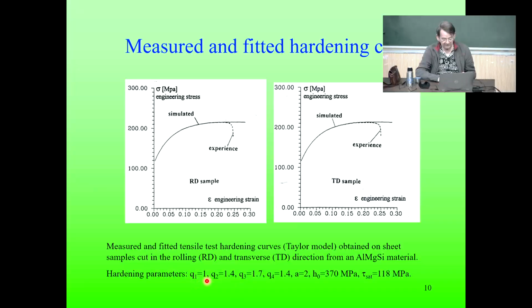We have the 4 self and latent hardening parameters. We have the initial strength of the material. Tau sat is the material tau sat, and then the rate hardening, and then the A parameter. That's it, and it is reproducing perfectly. Once these parameters are obtained, that's a separate exercise, then they are used in the polycrystal model for all the other strain paths, hoping that it's also valid for all strain paths. The result will be a strain path dependent hardening curve.